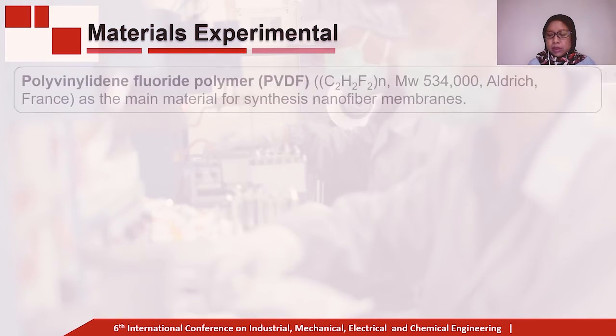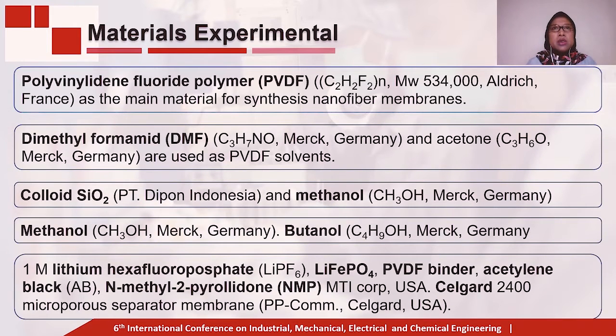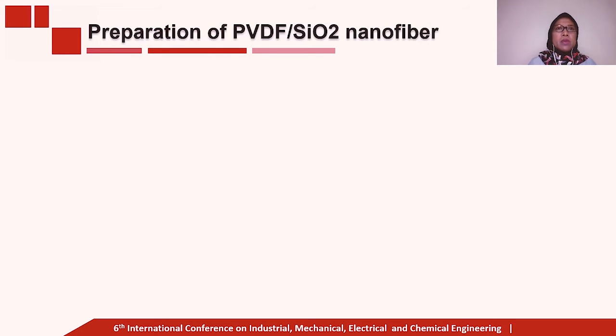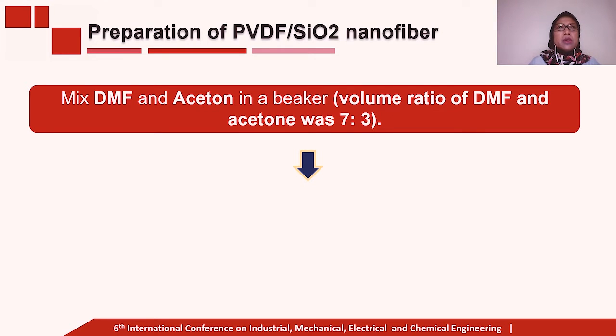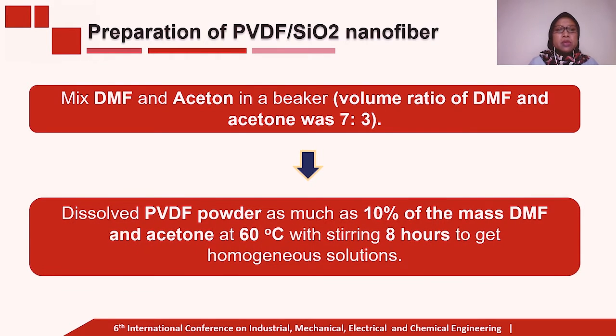This is the material used for PVDF SiO2 nanofiber preparation. The preparation of PVDF SiO2 nanofiber. Step 1 is preparation of the precursor by mixing dimethylformamide and acetone in beaker, and then dissolving PVDF powder 10% by mass at 60 degrees C, stirring 8 hours until get homogeneous solution.